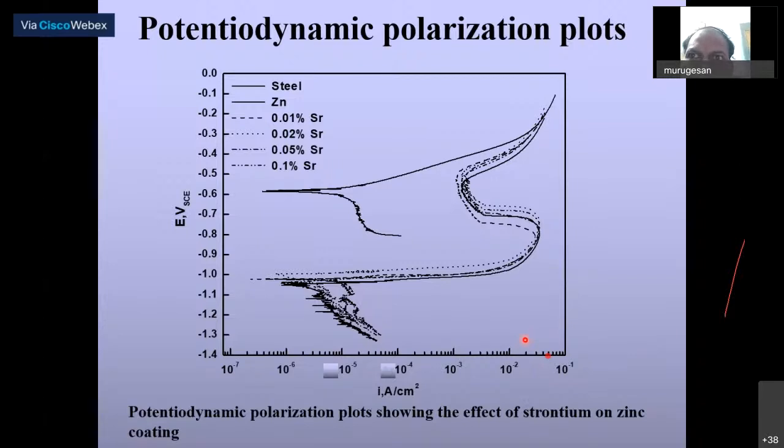Okay. Now I understand what you're telling. So what is the potential range where you can draw the Tafel line? This is your question? Yes, sir. Okay, so not the potential range to carry out the experiment, right? You're talking about the potential range. Suppose it is very close to the I-peak, then the slope will be horizontal. If you go away, it will become vertical. So the appropriate potential is very essential. Then only we can get the correct Icorr value. So that's very important. See, that is very important.